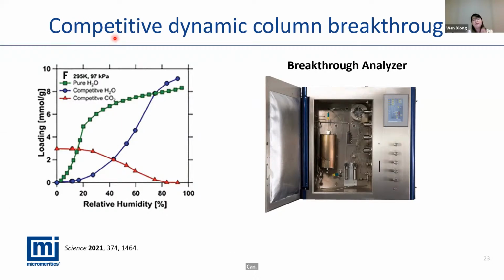adsorption. For example, if we have CO2, water, nitrogen, hydrogen, different kinds of gas mixed together going into an adsorbent, then the adsorbent has different selective adsorption capability for different gases. So a mixture of gases can show some competitive adsorption on the adsorbent. When we need to check the adsorptive behavior under real industry conditions, like a mixed gas mixture, we have to think of using the breakthrough analyzer to do the dynamic column breakthrough analysis.